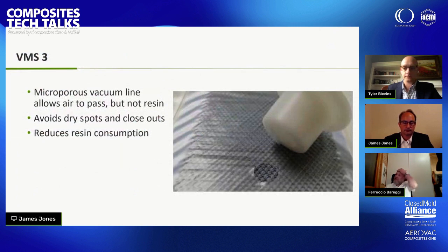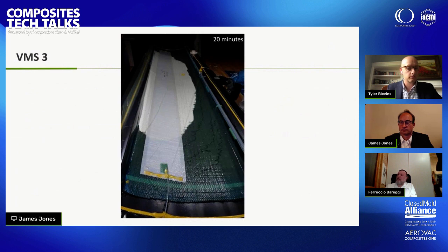Yeah, a very peculiar product we have developed specifically for infusion and mainly for wind energy infusion is a microporous vacuum line, VMS3 or VMS4, that is available in various widths, with or without perforated release film on the surface in contact with the part. This product, positioned directly on the part in critical areas, is granting the optimum vacuum, avoiding dragging resin out into the vacuum hoses and giving a safe freedom of infusion network designing, avoiding dry spots. It's useful in the area where the laminate transitions from solid to sandwich, or to grant the vacuum and correct impregnation onto solid inserts, such as longitudinal reinforcing that can sometimes be made by already pre-polymerized pultruded sections.